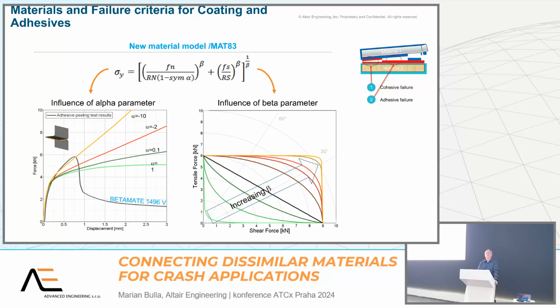How to deal now with the fracture criteria? We developed an equation to deal with fracture in different load scenarios, and the symmetry value, which helps to distinguish the peeling force. With rotation of one surface against the other surface, you see a reduction of the normal failure force. And this is what we figured out in this research project. And now you can use this kind of test for peeling and fine-tune these values here. So this allows you now to catch the peeling effect in addition to failure in normal direction and in pure shear direction.